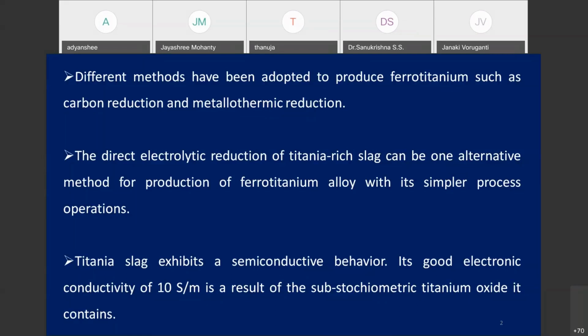Now, another important point is that after removal of iron, the iron concentration in your titanium slag is reduced, and in this case it is quite semiconductive. The slag shows semiconductive behavior. Its electronic conductivity is 10 Siemens per meter due to the presence of the titanium suboxides. So lower valence titanium suboxides provide some electrical conductivity to this material.